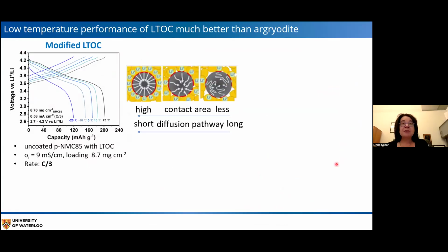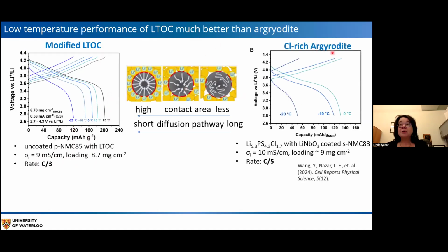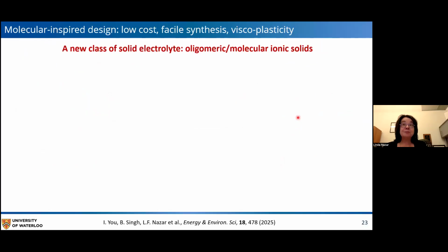And just to make a point about this low temperature performance, this is a modified lithium tantalum oxychloride, but it's basically similar. This shows a material with a conductivity of 9 millisiemens, loading of 8.7 at a C rate. And you can see that even at -20, we get really very reasonable capacity out of the system. Whereas in the case of a chlorine-rich argyrodite, which is the most highly conductive material we could prepare, at 10 millisiemens, similar loading, and even at a slower rate, we're nowhere close to that at -20. So this shows the benefit, especially as a catholyte, of having a highly conductive material.